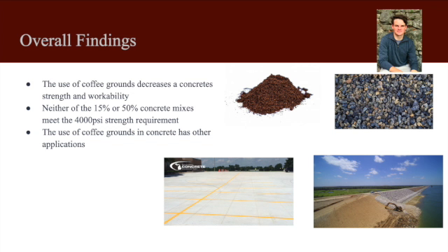We found that replacing 15% and 50% of our fine aggregate sand with coffee grounds is not realistic for parking lot concrete. This is because both mixes that use the 15% and 50% coffee grounds did not meet the minimum strength requirements for concrete used in parking lots or driveways, which is 4,000 psi. Actually, both of these mixes failed before they even came close to reaching 4,000 psi.